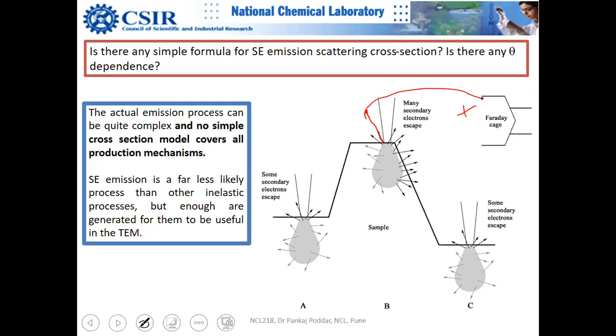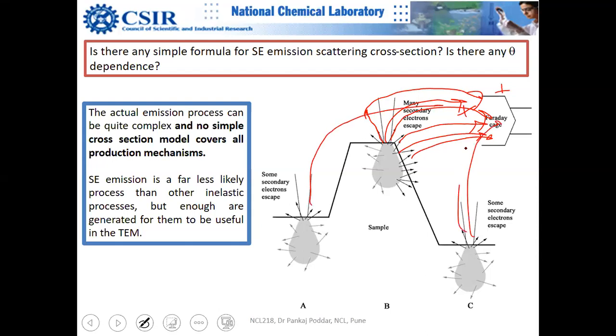A small amount of positive voltage is applied which speeds up the secondary electrons and pulls them toward the detector. This causes electrons to lose their directional information and energy identity, so they do not represent which atom they originally came from — further explaining why secondary electrons have no Z contrast.